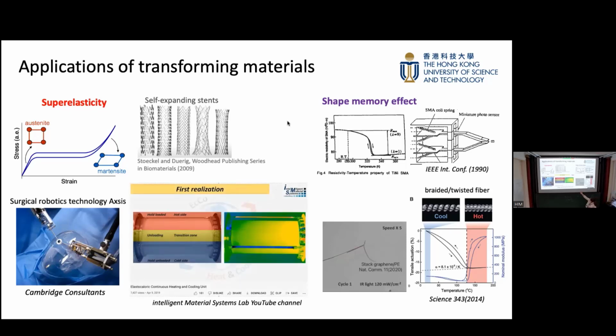This is due to the stress-induced phase transformation. When we pull it, it will release the heat, and when we release it, it will absorb the heat. And at the hot side, people just use some heat sink to get the heat away, and then let it absorb a lot of latent heat during the reverse of the phase transformation, and people use it for solid state refrigeration. And here, this is just some IR image, just to give some IR signal.